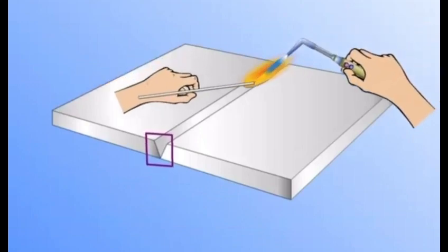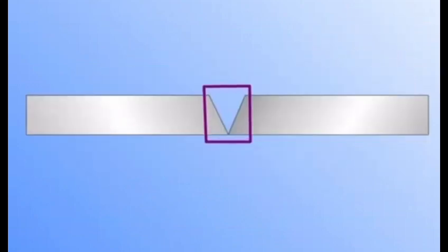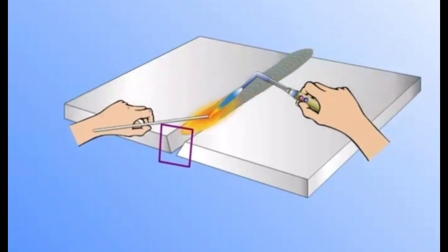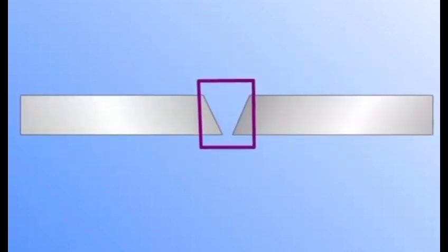This occurs due to incorrect joint preparation, root edges touching each other, and if V preparation is too narrow. To avoid this, prepare and set up the joint correctly and maintain appropriate gap at the root edge.